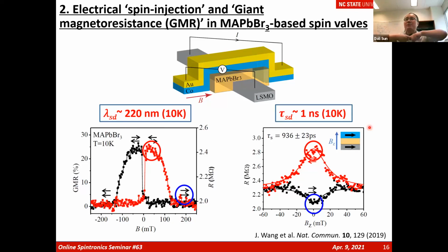So that came to the same conclusion, compared to our previous results: how a material has such a strong spin-orbit coupling, right? Spin physics, the intersystem crossing. Meanwhile, we have a decent spin relaxation time. It's supposed to be an inverse correlation, but now they both exist in one material. So that gave us the hypothesis, maybe there's another effect dominating the spin-dependent phenomena here. That's the hypothesis: the Rashba effect plays an important role here.